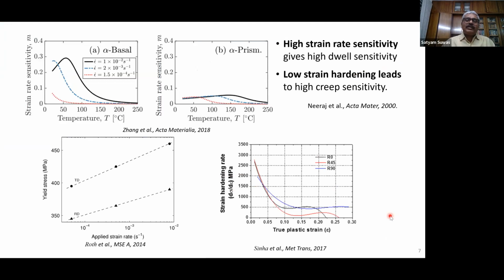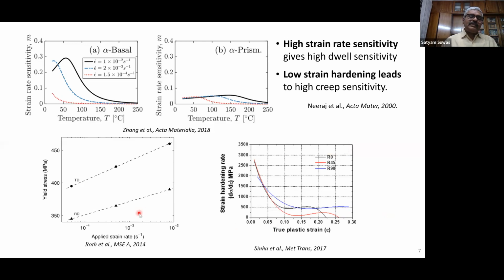So as I mentioned, there have been very many investigations on this. And one particular thing that has been found is high strain rate sensitivity gives high dwell sensitivity. And if there is a low strain hardening in the material, then it leads to high creep sensitivity. In both cases, it is damaging in terms of occurrence of damage in fatigue. So with this, now we wanted to investigate how the in-plane anisotropy in mechanical property affects the dwell fatigue response.